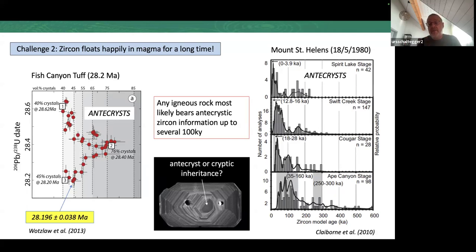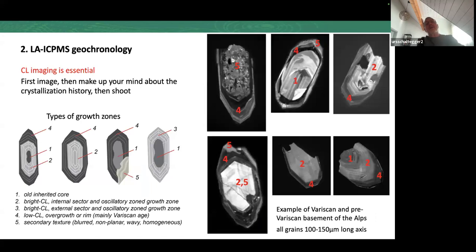So this could be antecrystic zircon, which just got recycled in the magmatic system. But don't forget that there's also the possibility that there's some really very small core in the center, because zircon has to nucleate from something. And so there could be a nano inclusion of an inherited core, which moves your analysis slightly, but definitely would not move sufficiently that it would leave the concordia. So they stay analytically concordant.